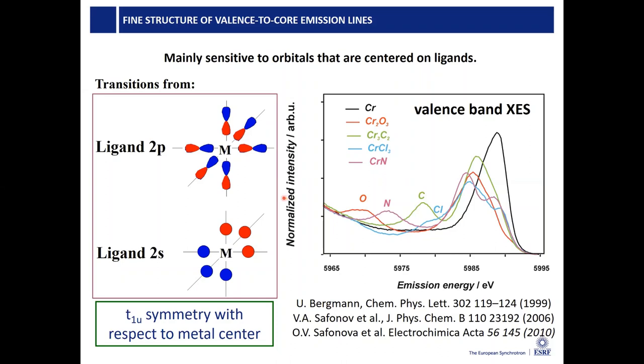I'm sure this is the last thing that I showed. Maybe then I explain it a little bit better. The valence to core emission lines come from mixed orbitals. This is the metal ion here in the center, and the 3d orbitals, also p orbitals, on this metal ion form together with the ligand orbitals. These are six ligands around, and these are two p orbitals on the ligand. They form molecular orbitals that are composed like a linear combination of atomic orbitals. They're composed of the metal orbitals and the ligand orbitals. This can happen by mixing the ligand 2p orbitals with the metal orbitals, or the ligand 2s orbitals with the metal orbitals.